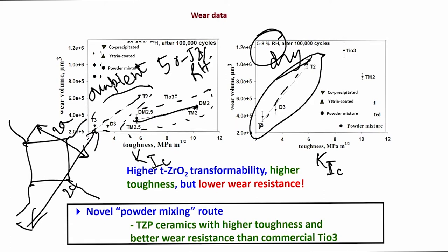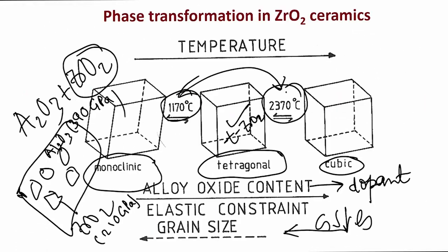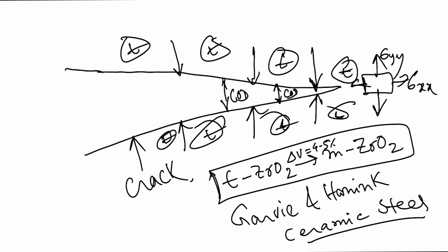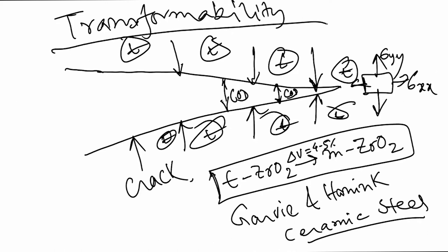So, what it means is that it is important to tailor the fracture toughness properties, because higher fracture toughness essentially means higher tetragonal zirconia transformability. Transformability means, if you go back to my earlier sketches, the ability of tetragonal zirconia to transform to monoclinic zirconia in the crack tip stress field. So, the higher the transformability, the higher would be the potential of tetragonal zirconia to transform to monoclinic zirconia. This is very important for you to remember.